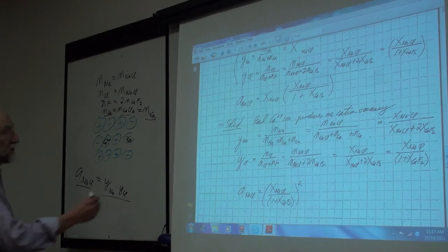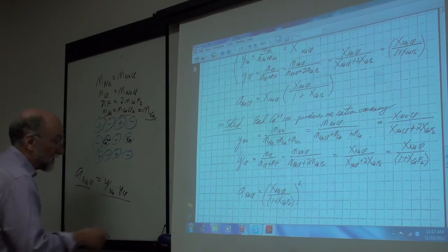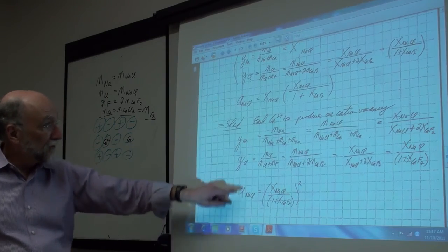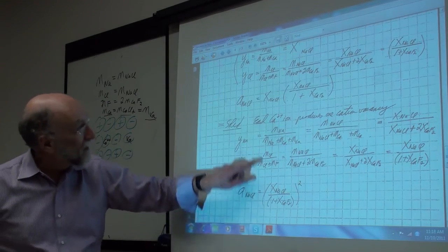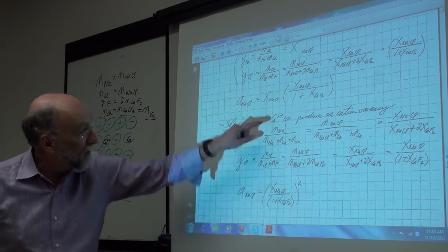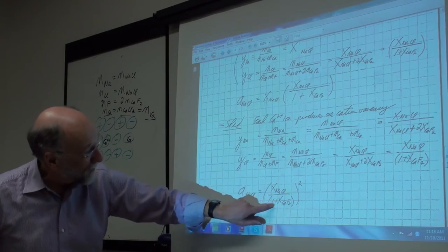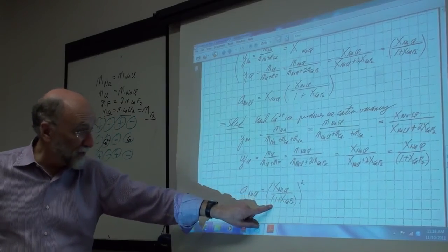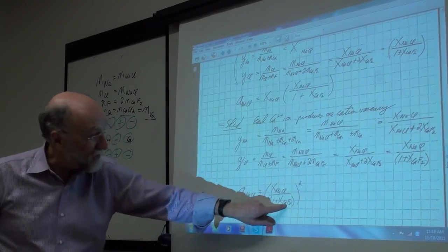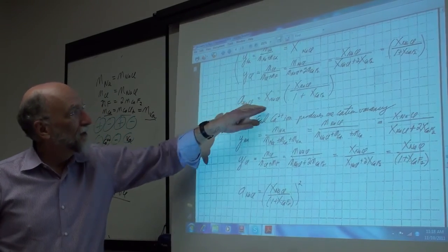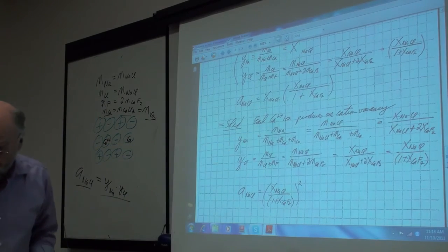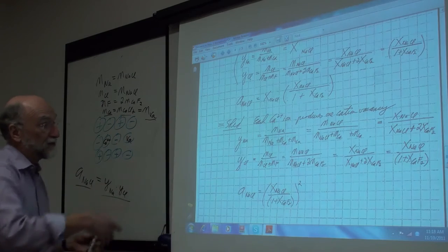What's this going to do to the, okay, so you see that if you compare these two equations, the difference between the two is that this equation here has one more denominator, 1 plus X calcium chloride, in the denominator. So the denominator is greater than 1. This 1 plus X calcium chloride is always greater than 1 in the denominator, so that lowers the activity of sodium chloride. Okay, so this always means that this is total entropy.